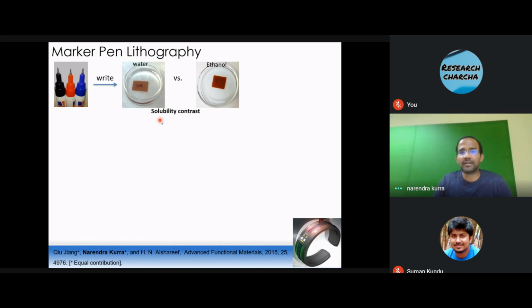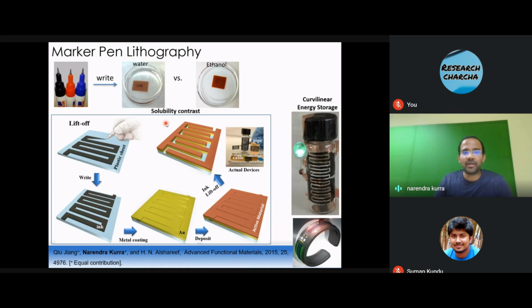By exploiting this concept, we have constructed microsupercapacitors. So here we made this serpentine-fashioned ink pattern as shown here. We use a roller guide to make nicely written patterns. So this is the ink we have drawn, and again we do metallization here, like titanium and gold, followed by deposition of active material and then lift-off. We get nice interdigitated electrodes shown here.